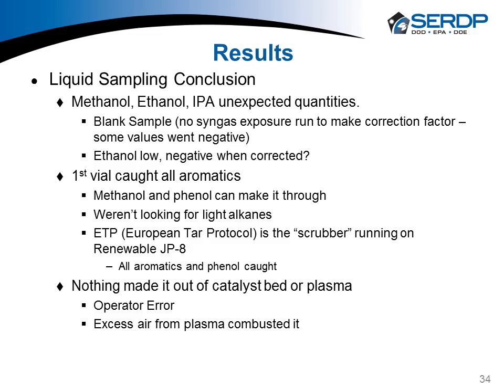So conclusion from the liquid sampling, we did see methanol, ethanol, and isopropyl alcohol more than we wanted or expected. We ran blank samples to make a correction factor, and that's what drew some of the samples low or negative when corrected. One thing we can say is the first vial was catching all the aromatics. Methanol and phenol can make it through. We weren't looking for light alkanes, which I'll talk about later, which is something we should probably have been doing.